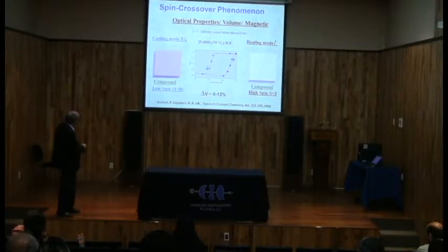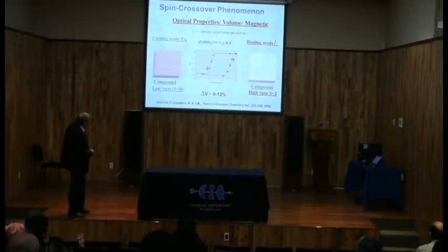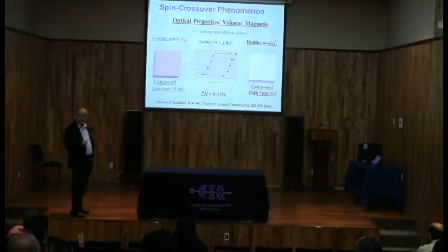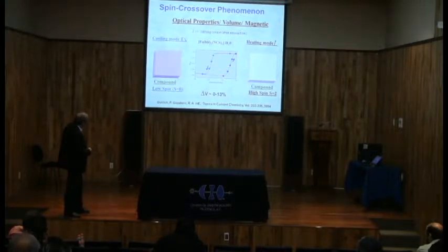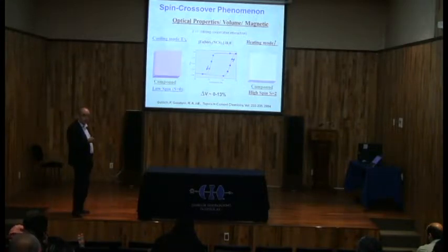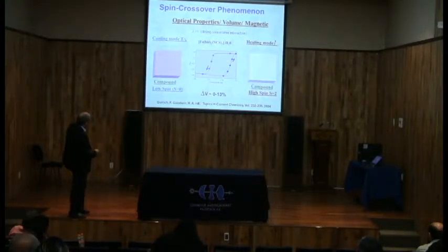And if you measure the proportion of high spin as a function of temperature, you will see that you will have a hysteresis loop, okay, like that. And then in this system you have a hysteresis loop. When we have a hysteresis loop, that means that at fixed temperature, you can have two states, 0, 1, okay? You have the memory effect in the system, because at fixed temperature you can have two states, and then you can reach one state or the other one, and the occupation of one state depends on its history, okay? And then as I told you, you can have a huge change of the optical properties. You can go for example, for this system, from white to pink, change of spin, change of the volume.